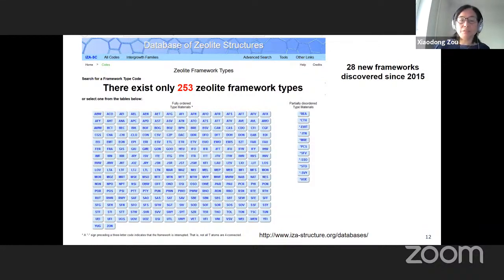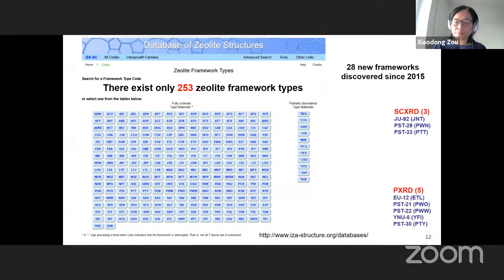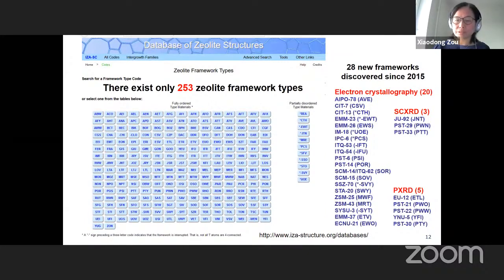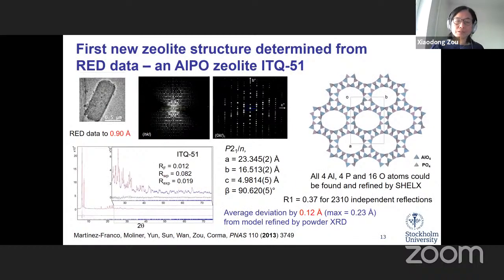The reason is that many of the zeolites crystallize as tiny powders and are difficult for single crystal X-ray diffraction. I'll just give you an example: there are 28 new zeolite frameworks discovered since 2015. Only 3 of them were determined by single crystal X-ray diffraction, and 5 of them by X-ray powder diffraction, and all of the rest, 20 of them, were discovered by electron crystallography. So this shows the power of electron crystallography for studying the structures of zeolites. Many of them were discovered before, but their structures could not be solved because of the limitation of the existing techniques.